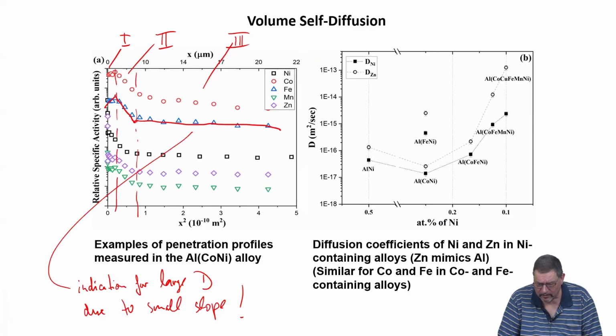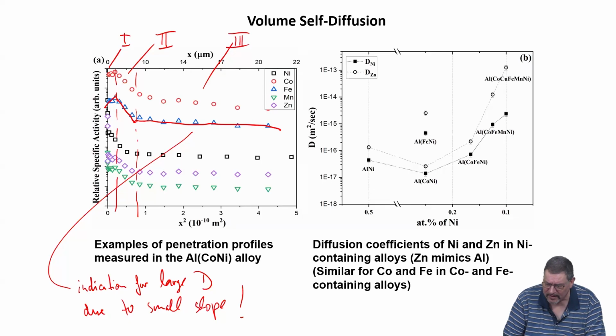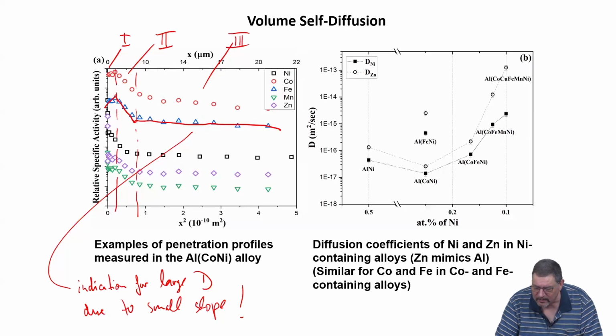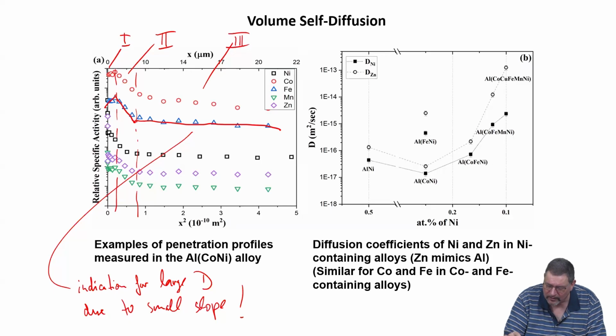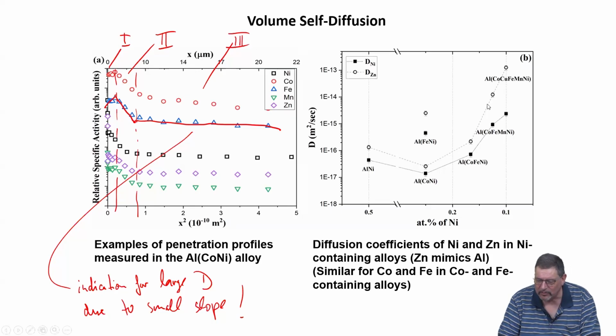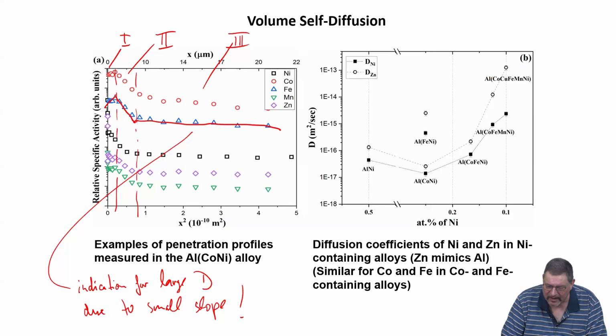Then obviously one can do these measurements for all the different systems, the binary, ternary, quaternary, and quinary sublattice, and this is the result shown here. Diffusion coefficients of nickel and zinc in nickel-containing alloys as a function of the atomic percentage of nickel. And the tendencies are similar for cobalt and iron in cobalt and iron-containing alloys. And you basically see that when you look at the tendency going from rather pure to rather high entropy sublattice alloying, the diffusion coefficient goes up. And it goes up strongly.